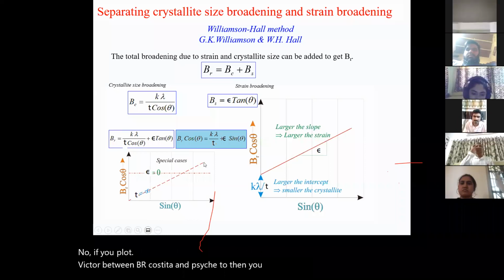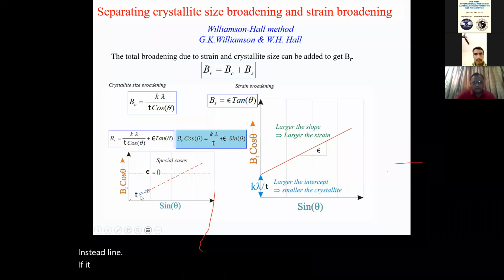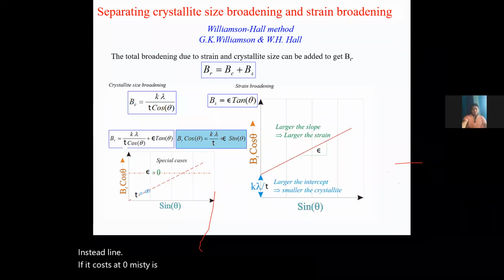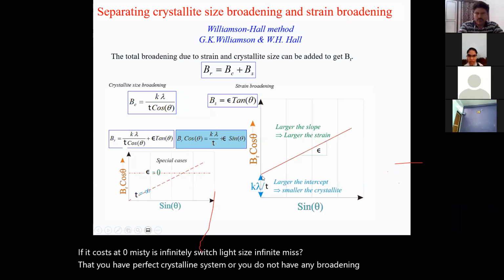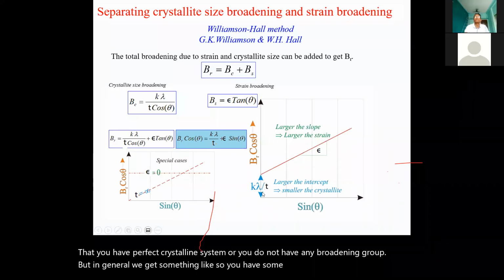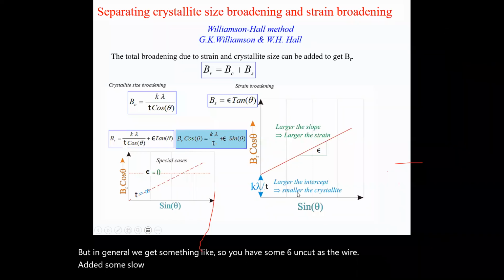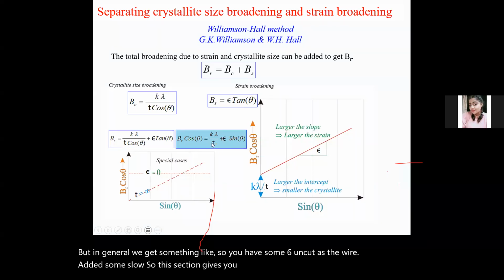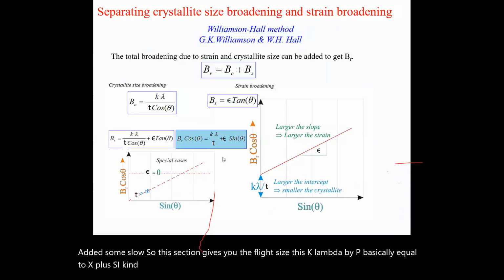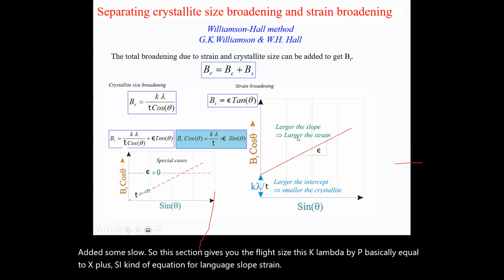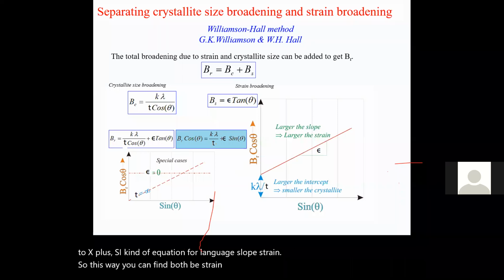Okay. Now if you plot a curve between BR cos theta and sin theta, then you get almost a straight line. Okay. And the straight line, if it cuts at 0, means T is infinite, means crystallite size infinite, means that you have a perfect crystalline system, or you do not have any broadening due to this. Okay? But in general, we get something like that. So you have some intercept on the y-axis and some slope. So this intercept gives you the crystallite size, this K lambda by T. So it is basically a y equal to mx plus c kind of line equation, and your slope gives you strain.